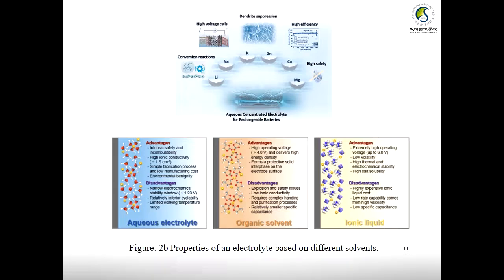The major drawbacks of aqueous electrolyte are that it shows only a narrow electrochemical stable potential window of around 1.2 volt, relatively inferior cyclability, and a limited working temperature range. In the case of organic solvent, the disadvantage is less ionic conductivity and relatively smaller specific capacity. And the ionic liquid electrolyte shows low specific capacity when compared to all the others.